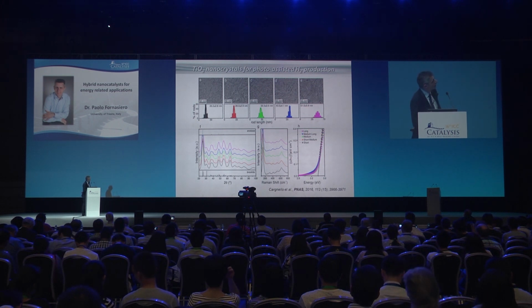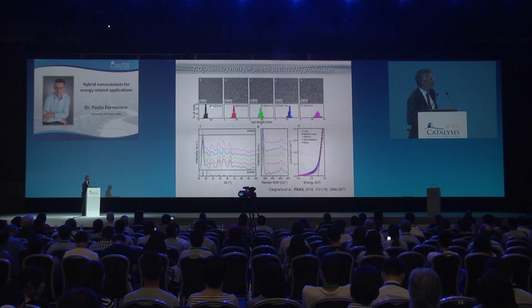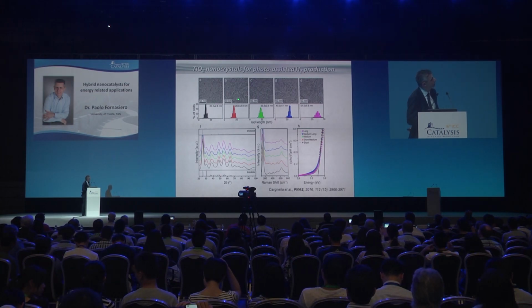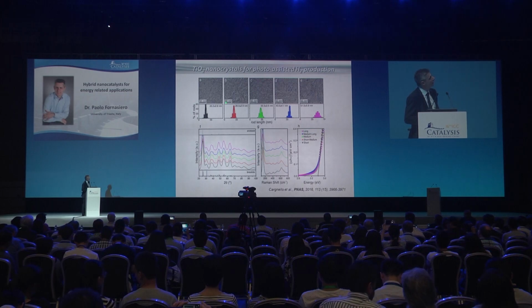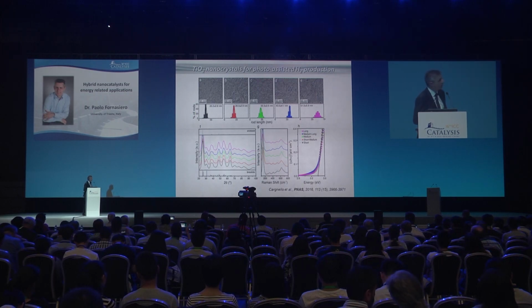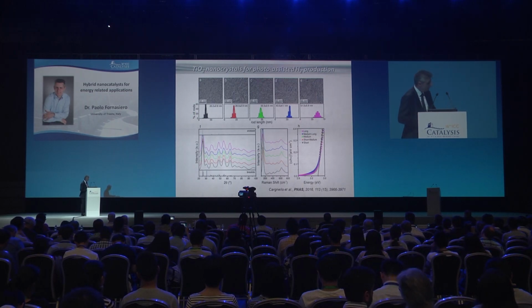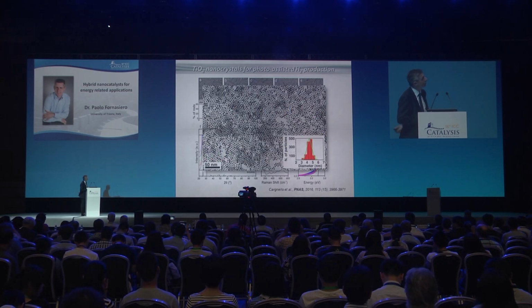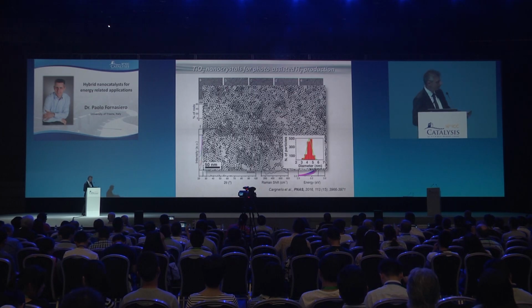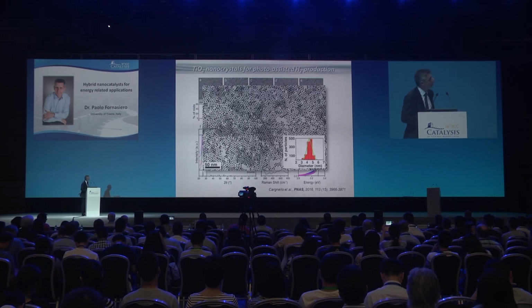In this case, we prepared nanorods of brookite, of the same thickness, and we were able to change just the length of the nanorods from 20 to 50 nanometers. And those are really homogeneous materials. We deposit a co-catalyst, platinum nanocrystals, a tiny amount of platinum.